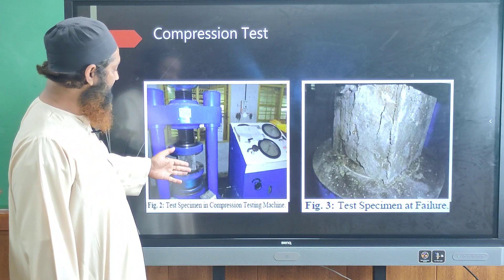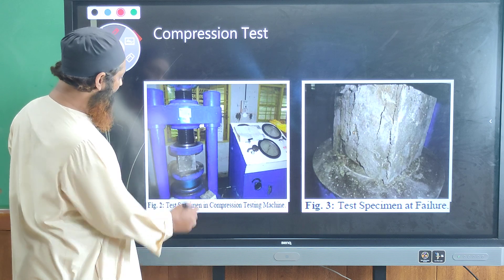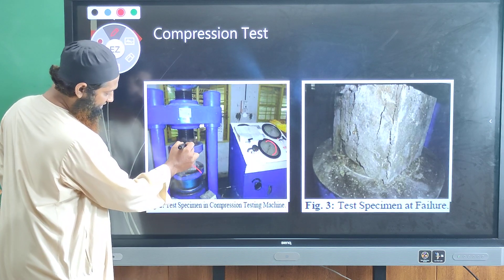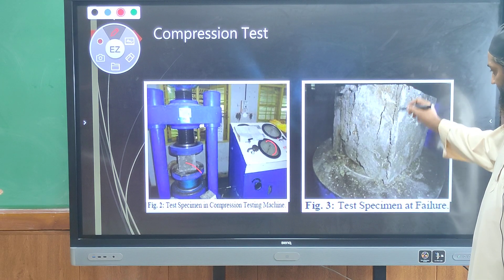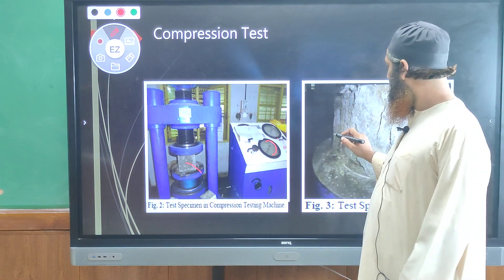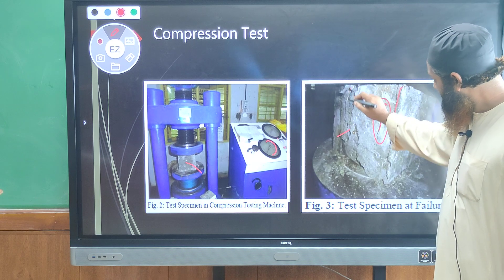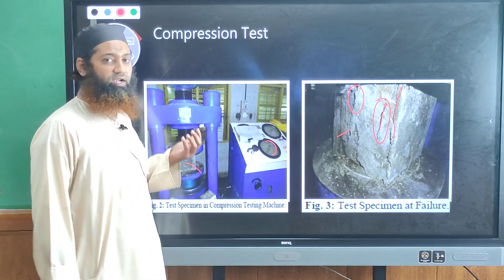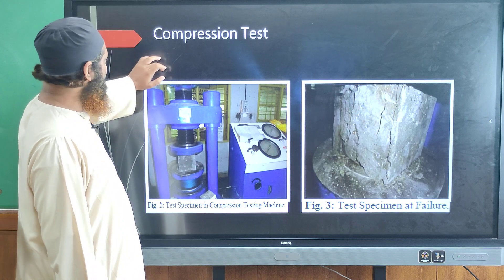This is how the compression test is done. The mold is prepared and put into the compression testing machine, where the load is applied from 40 tons up to 400 tons, gradually increased. Once the mold gets slightly crushed and cracks form, the testing machine is stopped and we record the strength achieved by this recycled aggregate concrete.